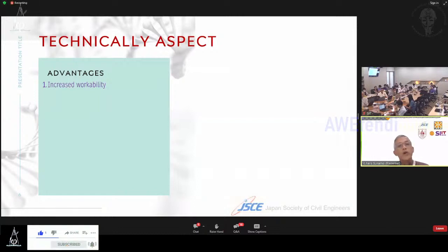The first is improved workability. So we can increase the slump of fresh concrete. In our product, some concrete that uses high volume fly ash behaves like self-compacting concrete. So the slump is very high. This makes it easy to cast the concrete on site. Second, decreased bleeding and segregation. The physical characteristics of fly ash can improve the cohesiveness of fresh concrete.